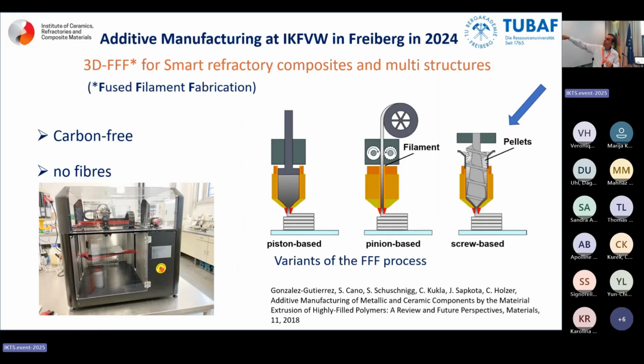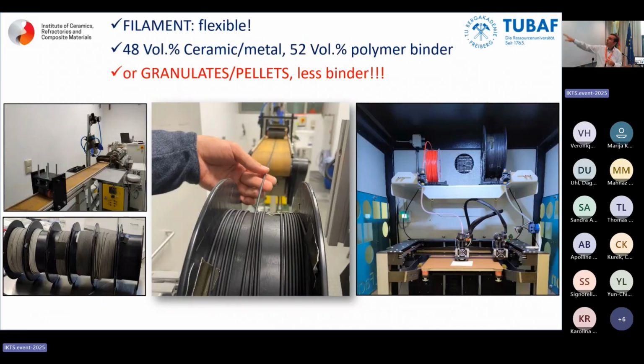Okay, 2024, my guys are experts today to print filaments or based on filaments. Of course, you can cut also the filaments and go to pellets. And it's much more easier because you don't need the flexibility of the filament. And as you know, our materials based are not flexible. And in this kind of issue, you can use much less binder. You will see this tomorrow, how we can print or how the printer is. You can make our own filaments, but keep in mind, granulates or pellets, much less binder.